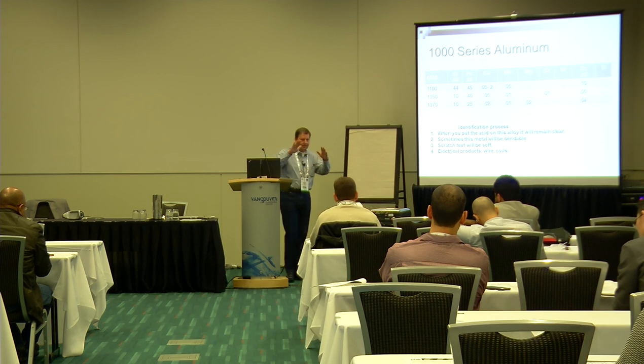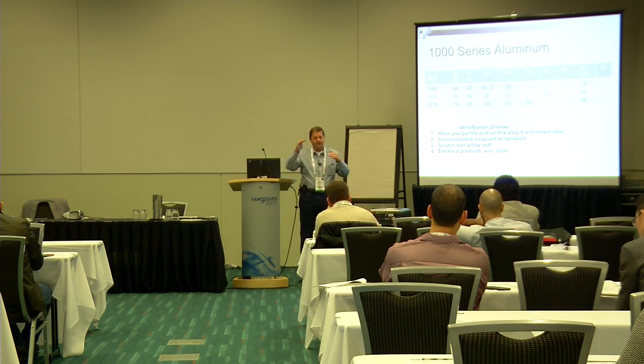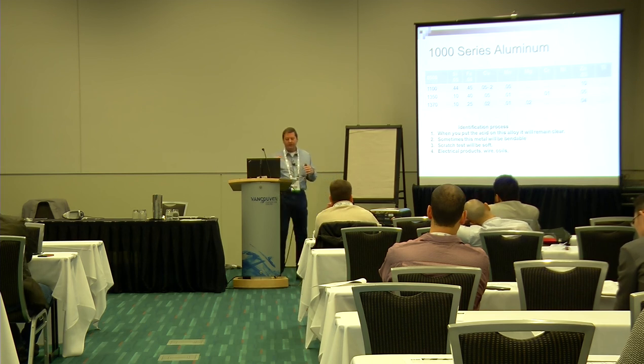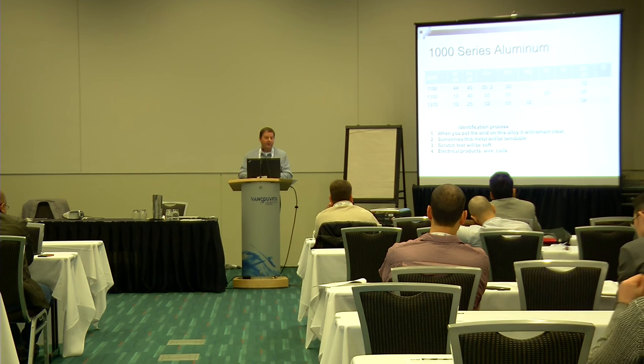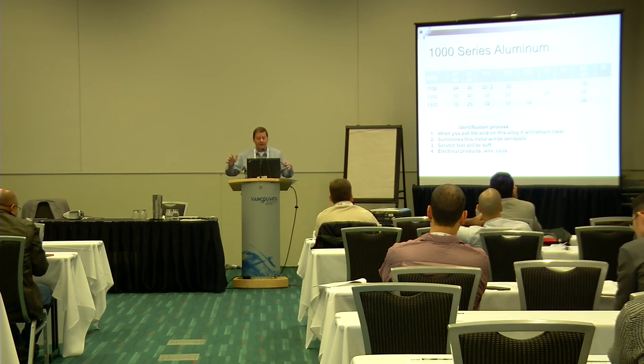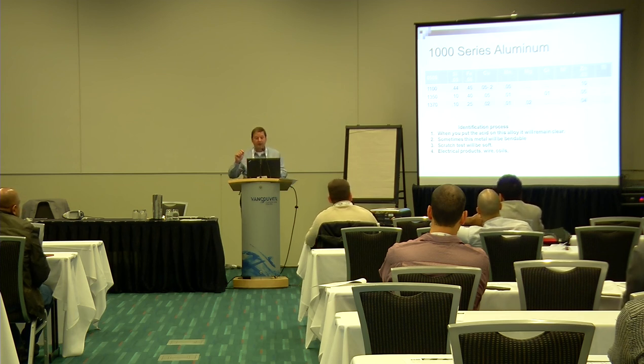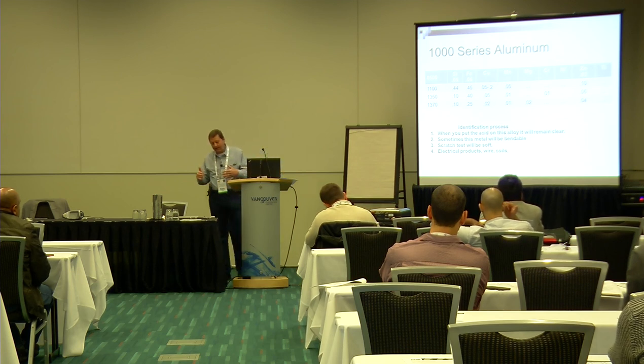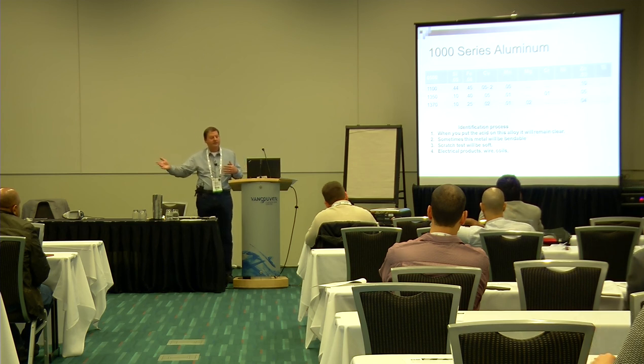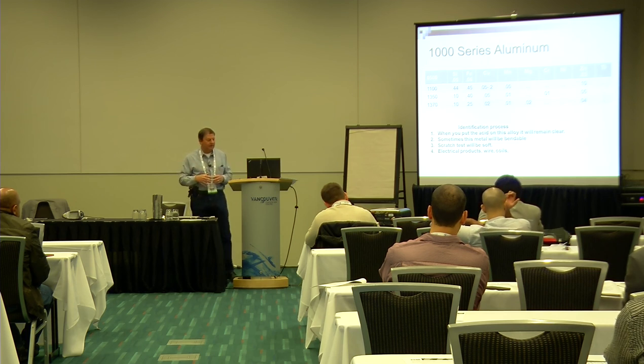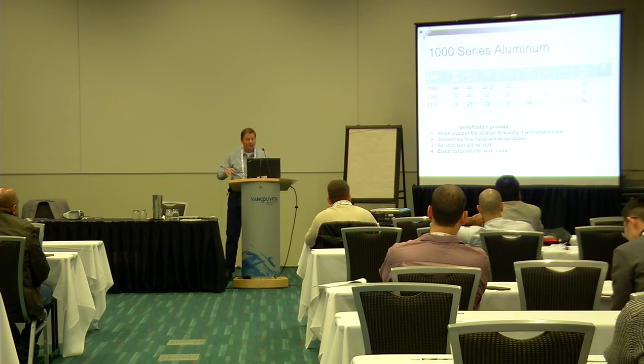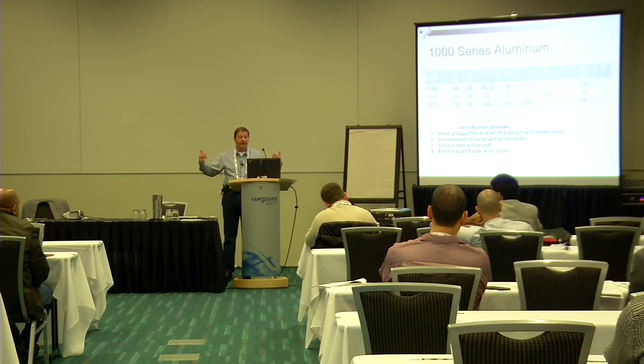Okay. Now, remember the slide before the other one was showing the different series. So this is that 1000 series. If you look at 1100, which is a very common alloy, look at the silicon, 0.45, iron 0.4, I'm sorry, 0.44, 0.45, copper 0.05, it's really small, 0.2, and then manganese 0.05. Just about everything that we do at our level, and even the primary, as Jim was alluding to, is never going to be written out. It's always by symbol. And once you've worked with them for a while, it'll be easy for you to see it. Now, the zinc is 0.1. So now what we're looking at is the remainder is all aluminum. So that's something that's good for us.